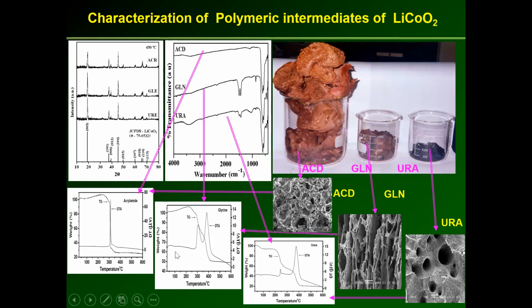And from the same pictures we can also see why this one gives only one single exothermic peak, while the others give more than one. You can see that here the pores are fewer, but they are higher flake type, so it is easy to burn. Whereas here the pores are very big, much bigger. The nitrate will come out, but their walls are very strong. You see that the walls are very strong; this is stronger than this one, actually.